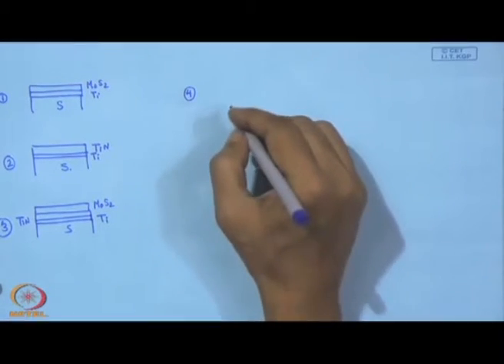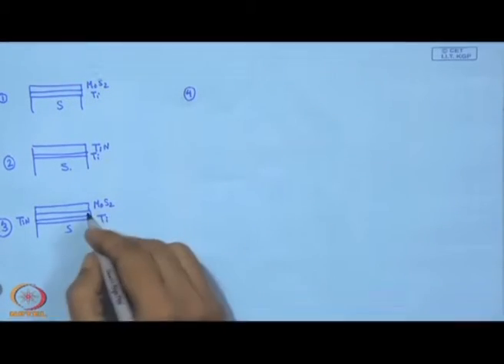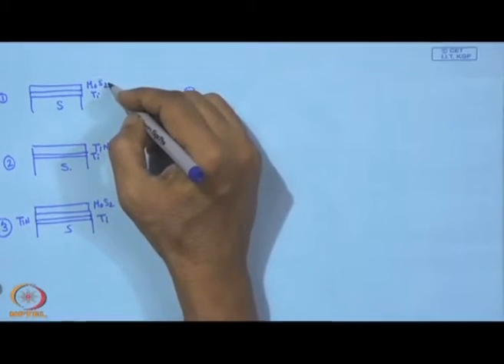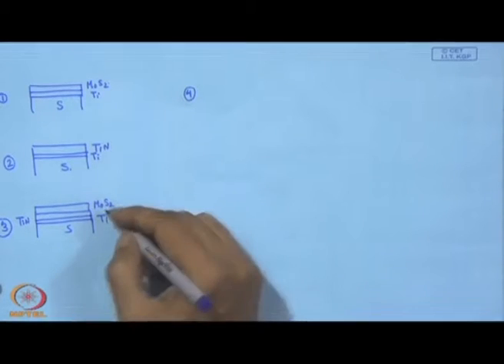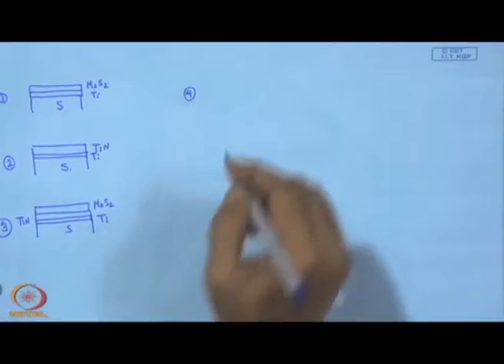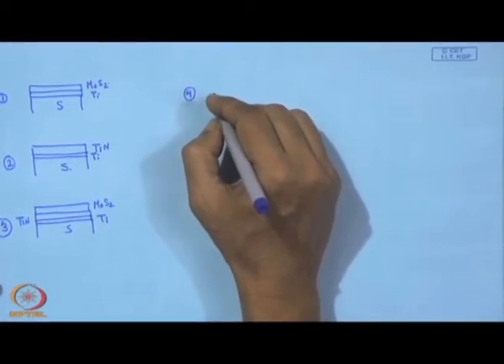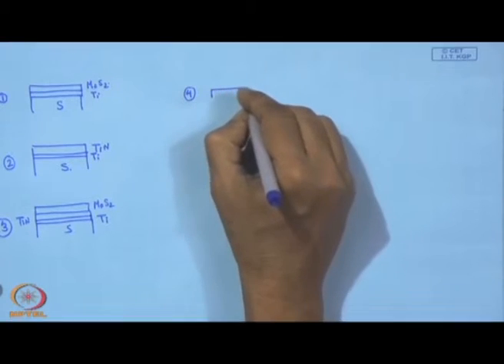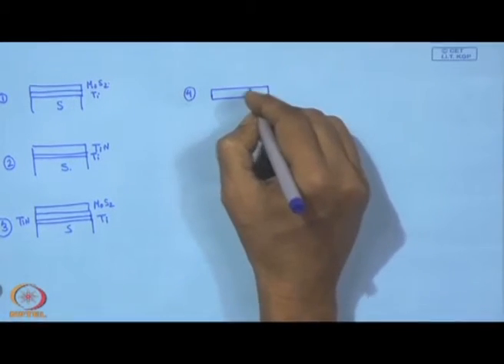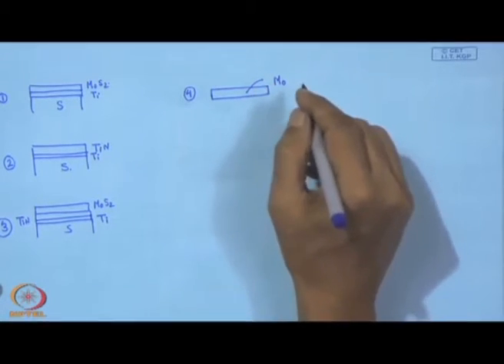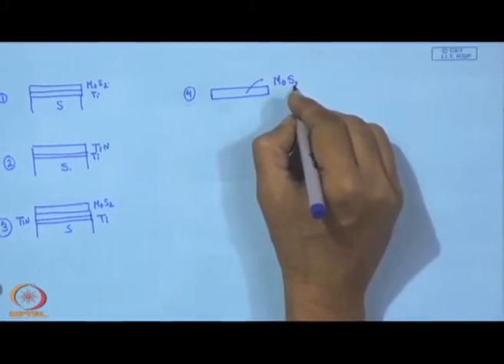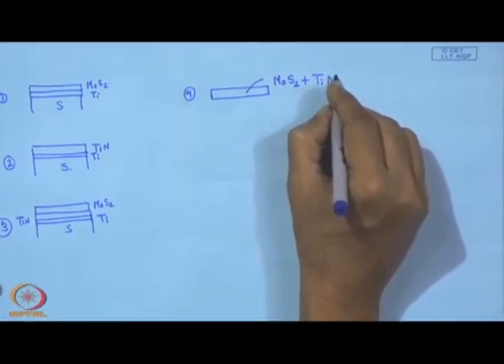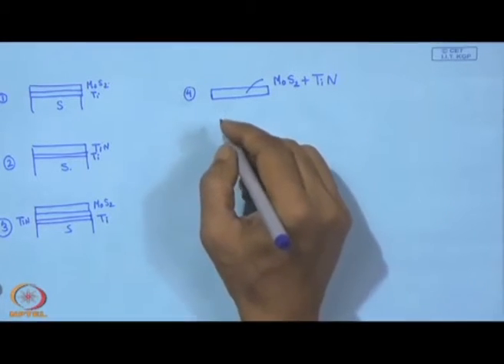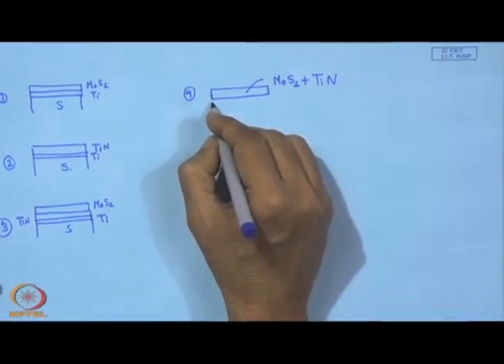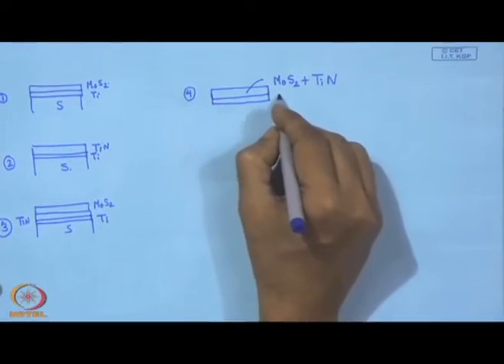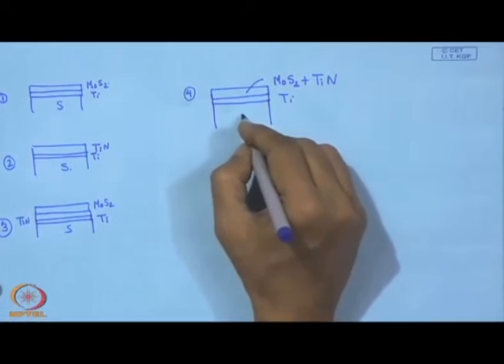Now, this is a combination, it is no more a monophase. The earlier ones are top monophase, but this is going to be a co-deposited coating. That means, on this coating we have both MoS2 and titanium nitride, and under this we have just Ti, followed by the substrate.